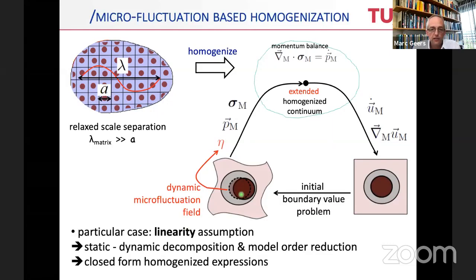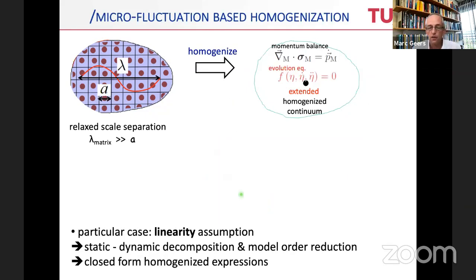If you now add linearity, which was one of the assumptions used in many of the other methods as well, all of a sudden we can do much simpler than this. We can do a static dynamic decomposition, combine that with a serious reduction of the model, and end up with closed form homogenized expressions. In my sketch, it would mean that all of a sudden the solution to the computational homogenization is no longer needed, but something instead appears, which is an equation for the etas. And remember the etas, they're the amplitude of the fluctuation fields. And for this problem, the fluctuation fields are the resonance modes.